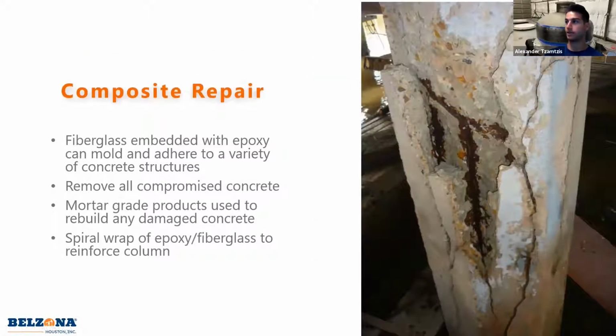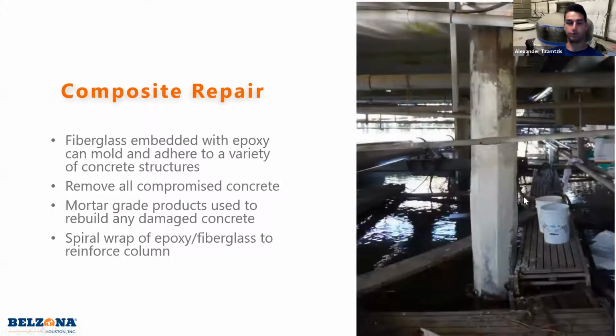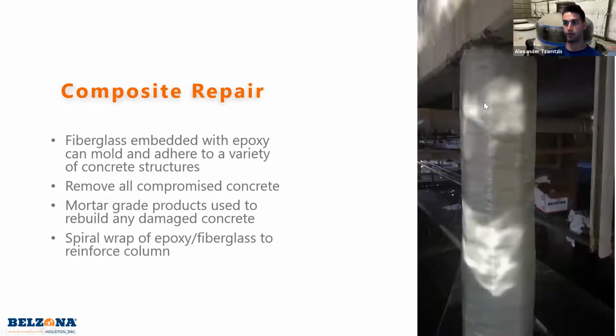This is a concrete pile, offshore, severely corroded, exposed rebar, cracking everywhere, vertical rebuild. So this was a good scenario to use our 4000 series high build. And they were able to sandblast and remove all the loose concrete, get down to the intact concrete and rebuild it with the 4141 high build concrete repair. And then we went over the top of that with a fiberglass resin wrap. And that's going to help with the concrete confinement. It's going to add a little strength to the concrete and give it corrosion resistance as well.